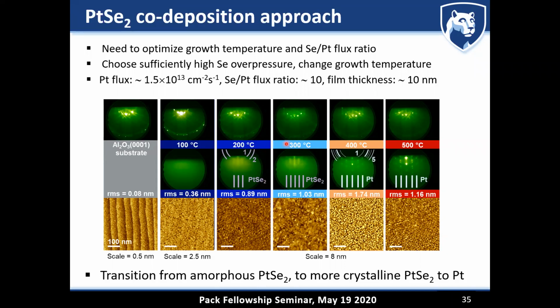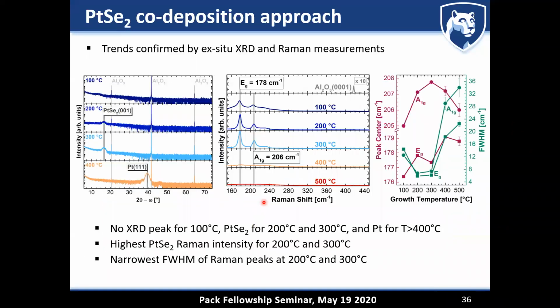And then as you increase the temperature, things get better. But at some point, you're losing the selenium because of this very high volatility. The selenium flux that you are generating is not high enough to maintain the platinum diselenide phase, and you're actually ending up with just platinum on the surface. Now, this very initial data was confirmed by ex situ analysis of the films we've grown. In X-ray diffraction, films grown at 100 degrees C barely have any crystalline phase. It's getting better at 200 and 300 degrees C, with the formation of a Bragg peak for platinum diselenide. And then as soon as you overshoot with the temperature, all the selenium is driven out of the film, and you're left with just a platinum film.